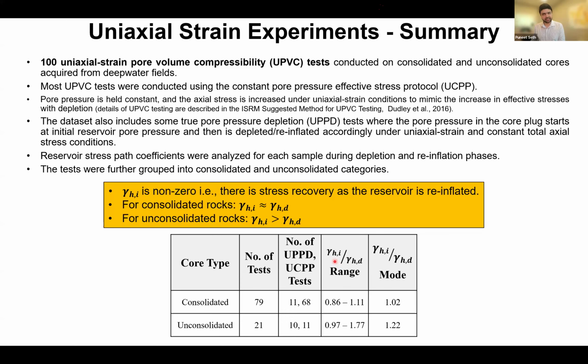This is the range of the ratio of the injection and the depletion coefficients. And as you can see for the consolidated tests, it's hovering close to the number one. And if you look at the mode of the data, it's quite close to one, meaning that the injection coefficient is almost the same as the depletion coefficient.